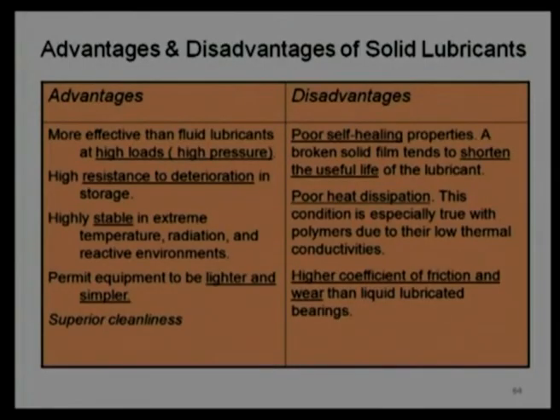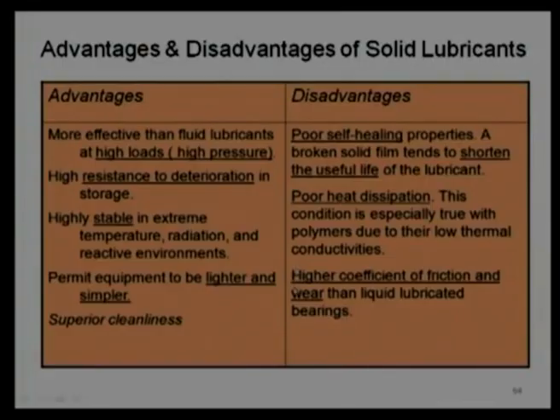Now, wear rate is somewhat subjective in this case. We say the wear rate of the solid lubricant itself can be counted as the wear rate, or sometimes people say the wear rate of the material which comes in the interface. Here the coating or the solid lubricant has been applied, and if it wears out, then it is going to give an unlubricated condition, and the wear rate will increase. So, first the wear rate of the solid lubricant and subsequently the wear rate of the metal at the interface will be high, and of course, the coefficient of friction will be high because they have a high bonding strength with this interface, and they do not give a very low coefficient of friction or low shear strength. Because of the solid state structure, they will have a higher shear strength compared to a liquid interface or liquid state.